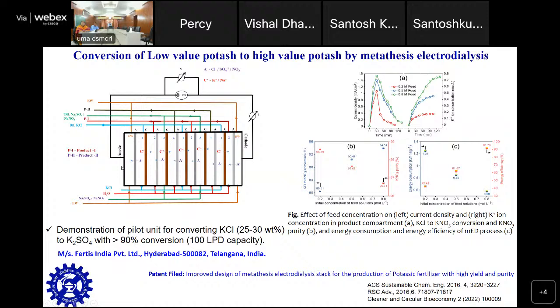Now, for the conversion of KCl to KNO3 or K2SO4, KCl is sprayed in compartment 1, sodium nitrate is sprayed in compartment 3, and in compartments 2 and 4, water is filled. So with time, electricity will pass, ions will start to migrate, and in compartment 2, the product NaCl will be enriched, and in compartment 4, potassium nitrate or potassium sulfate will be enriched. So after taking out the potassium nitrate or potassium sulfate, it can be dried by solar power, and then